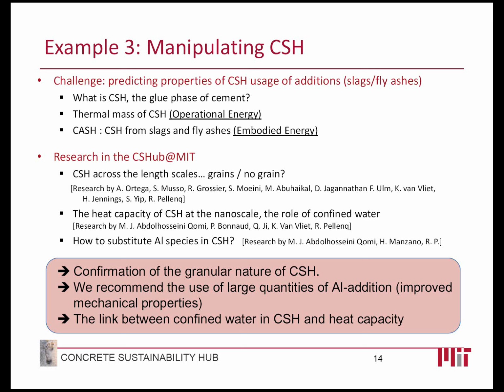So in our research, we will show you some new pictures of what CSH is at different scales, and see where the grains are. Then we go through heat capacities and some aluminum substitution in CSH. Our result is that yes, we do confirm the granular nature of CSH. We recommend a large use of aluminum addition because we found that it may improve mechanical properties, and we found a link between the water content in the final CSH phase and the heat capacity of the set paste. Next.